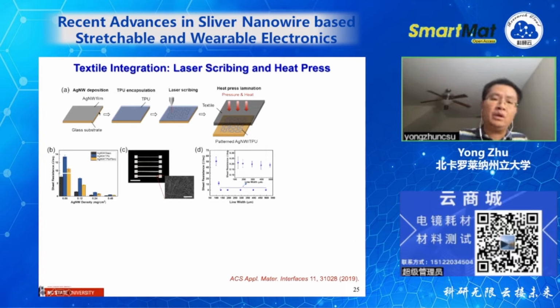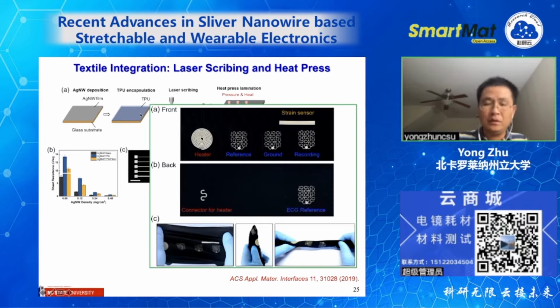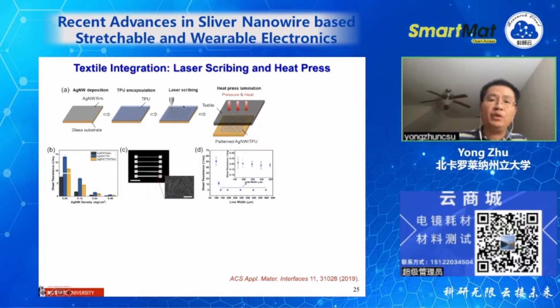What we have is, we just drop cast the nanowire network. In this case, instead of using PDMS, we use TPU, which is thermoplastic polyurethane, and then we use laser scribing. We use the laser to pattern the device. After that, we heat and press. We essentially laminate it to a fabric, to a textile substrate.